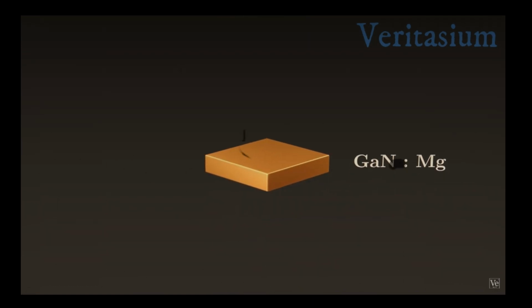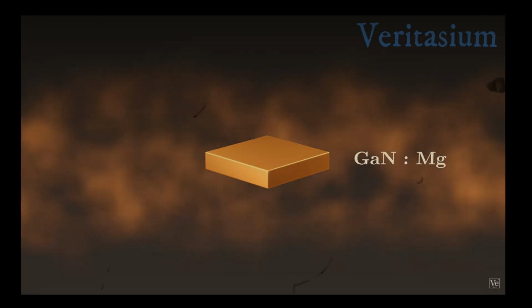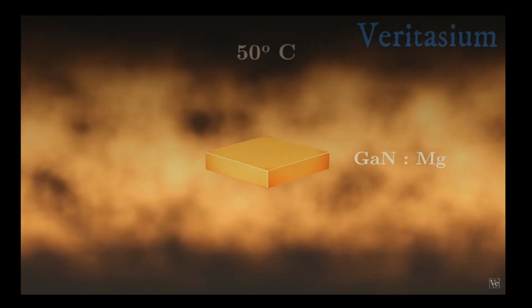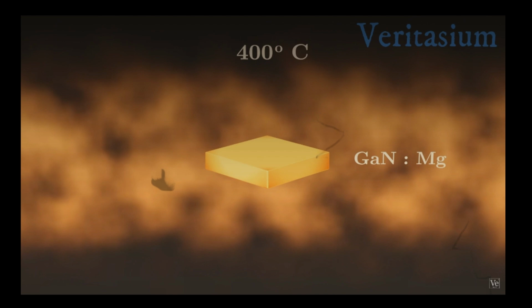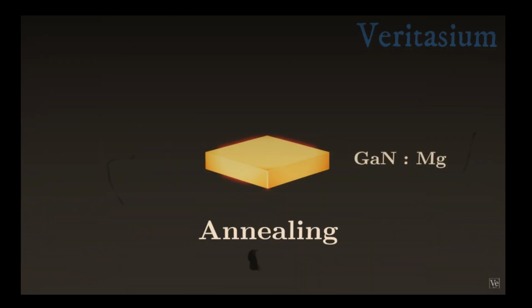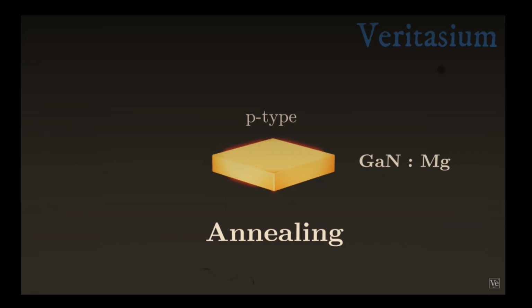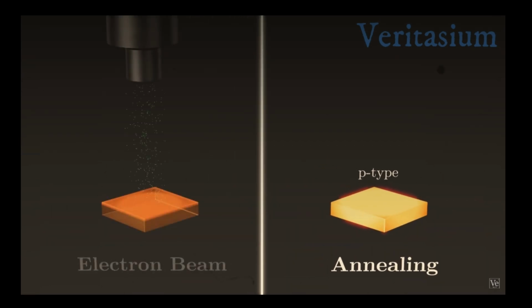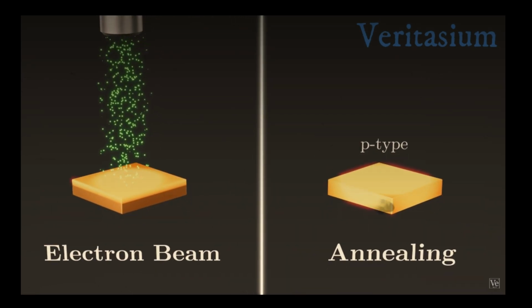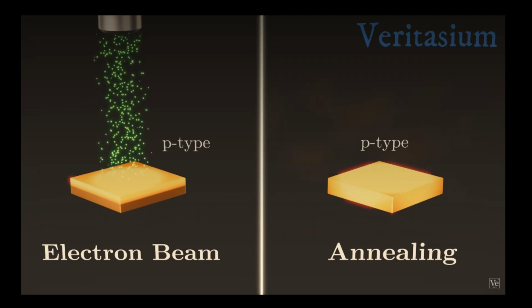So he tried heating magnesium-doped gallium nitride to 400 degrees Celsius in a process known as annealing. The result, a completely P-type sample. This worked even better than the shallow electron beam, which only made the surfaces of the samples P-type. And simply heating things up was a quick, scalable process.